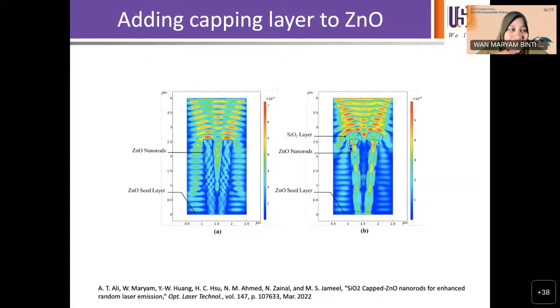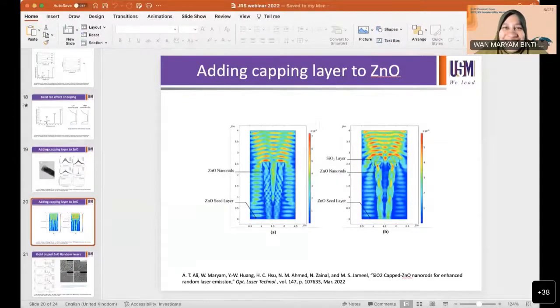What we actually notice is that the thickness plays a role. The thickness of the SiO2 layer is roughly a quarter of the wavelength in order for this effect to occur. If it's less than that or more than that, you still get lossy modes. There is that part as well that we noticed. Hope this answers the question.